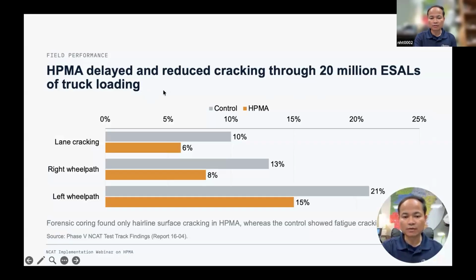Now, fast forward, after maybe the first research cycle, Creighton decided that they are going to fund the continued traffic, and so both sections N7 and S9 were trafficked up to 20 million ESALs of very heavy truck traffic. And then what we found is that you can see here the gray bar, the control, and the orange bar, the HPMA. You can see in all the areas that we monitor, the control section has more cracking.